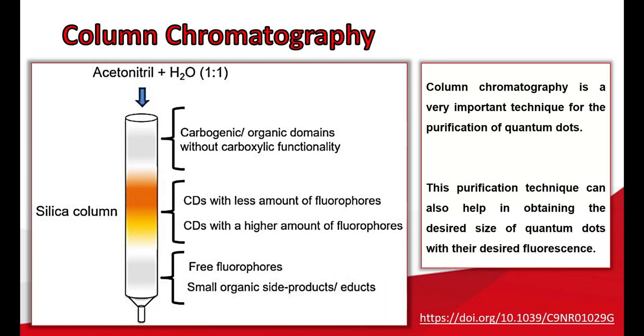Coming to the purification technique: we know that it is important to purify carbon quantum dots and any kind of molecules and materials after synthesizing. Purity is a key in the synthesis laboratory for best results. I'll be making a separate video on purification of quantum dots, but for now I would like to mention that it is important to use column chromatography when specifically interested in synthesizing red-emitting carbon quantum dots. If you are not using column chromatography, it might be possible that you are seeing a red color in the solution of carbon dots, but on irradiating with a UV source you are not seeing red fluorescence. So it is very important to use column chromatography to get the specific size range and specific fluorescence, specifically red.